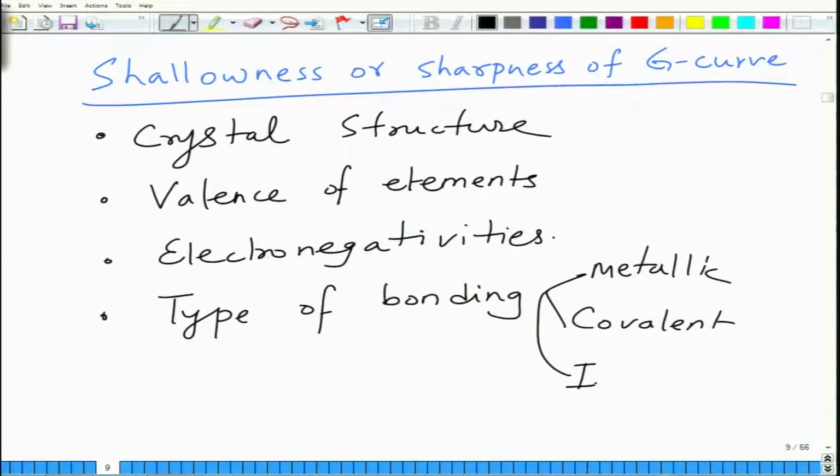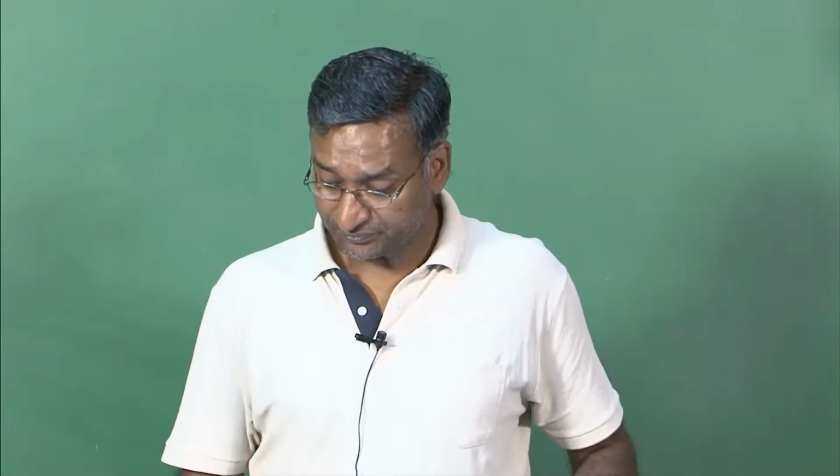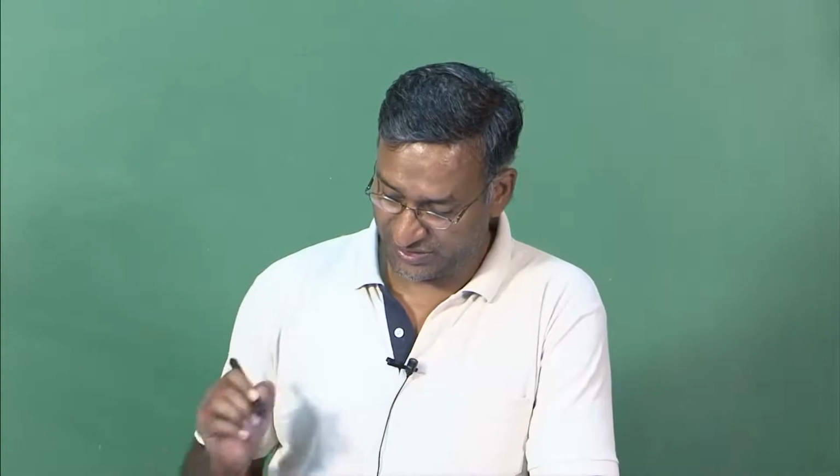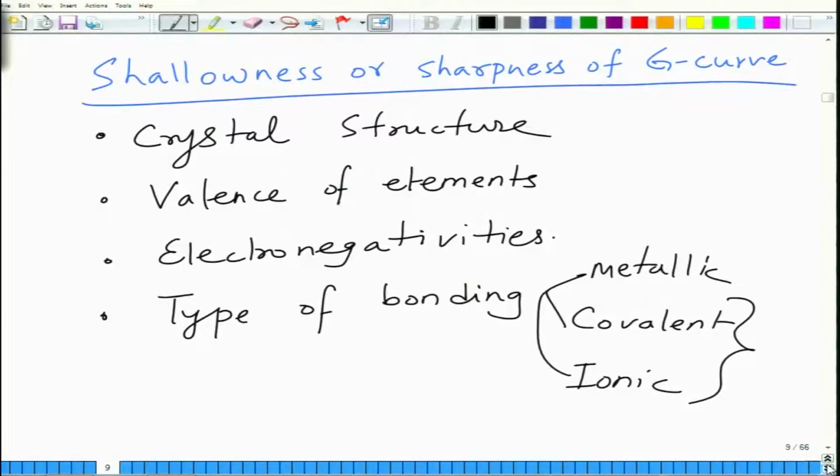or they have ionic. So, in general, compounds with metallic bonding will have more tolerance for compositional fluctuations as compared to compounds with covalent and ionic bonding. They are more stiff bonds with higher energy, and structures are far more stiff as well, and they do not allow too many composition fluctuations. Instead, when you change the composition, they tend to crystallize in different other forms.